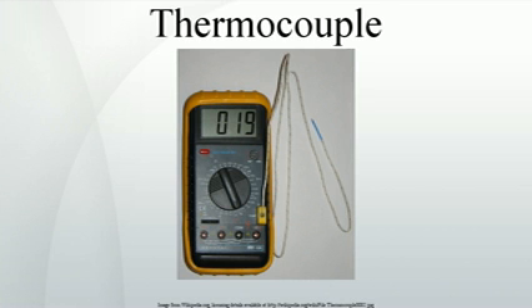Grades. Thermocouple wire is available in several different metallurgical formulations per type. Thermocouples are not merely defined by the composition. Thermocouple-grade thermocouple wire has been fabricated by an alloys manufacturer with deliberate care taken to match the material's curve to a standard curve. This can involve deliberate mixing in of impurities to dope the alloy, compensating for uncontrolled variations in source material. As a result, manufacturers may sell matched pairs of two lots of wire which together reproduce the standard curve, but which will show larger errors if combined with other lots.